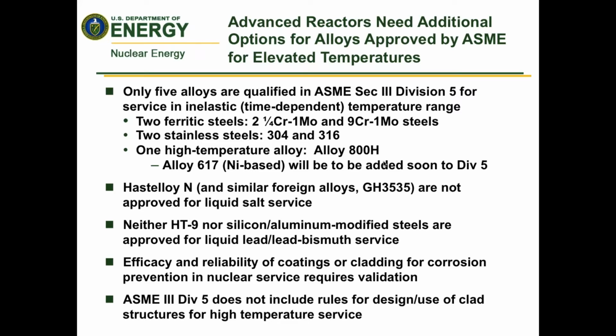Some of the questions that would arise from doing that relate to the rules for design and use of a clad structure where the thermal expansion and contraction of the cladding versus the base metal would have to be considered. Those rules do not exist in the code. Another issue that would have to be considered is diffusion of species through the clad layer into the base metal, and what effect that might have on overall corrosion. On the other hand, there have been some coatings that have been proposed and developed that appear to be self-healing, but they are developed on materials that are also not within the code.